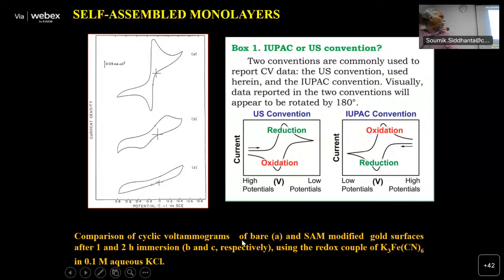For example, you can see now here A, B, C. This is again from our own experiments carried out almost 10 to 15 years ago. You have a gold electrode, you have potassium ferricyanide, ferrocyanide, you get a beautiful reversible peak. You can calculate all the quantitative parameters. When there is a self-assembled monolayer, meaning you have an octanethiol on the surface of gold, a complete monolayer, you will see all the redox processes are suppressed completely. Partial monolayer, you will get a little bit of activity.